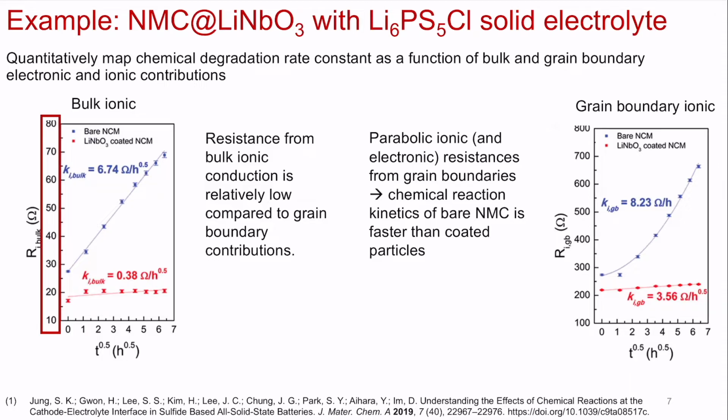But what's going to happen is upon discharge, you're now starting with a slightly different amount of your starting material composition, and that will induce another set of chemical decomposition products, as well as products from the electrochemical decomposition. Some of that's irreversible, some of that is passivating, as in you lose active material, but it stays there and it's stabilized, and other times it's not, it's quite reactive.